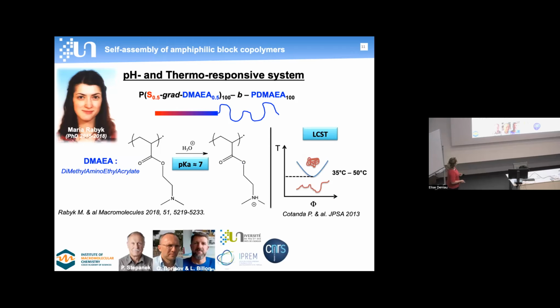So in this context, the first work I wanted to present is a pH and thermoresponsive system forming of copolymer with styrene as hydrophobic units and dimethylaminoethyl acrylate as hydrophilic one, which can be protonated upon the addition of acid and whose homopolymer can also be stimulated by the temperature with LCST ranging between 35 degrees and 50 degrees, depending on the molecular weight of the polymer.